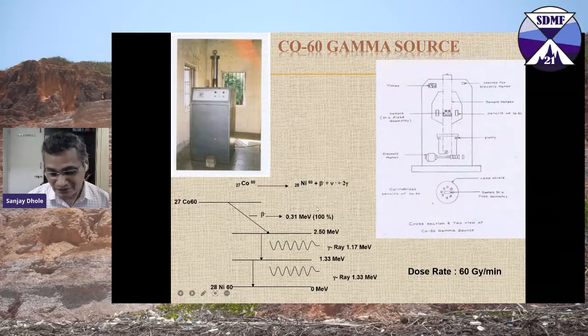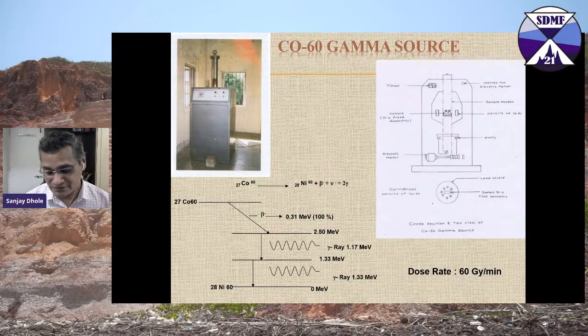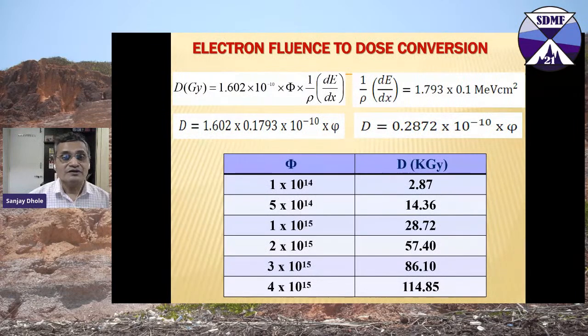So these are all the radiation sources which are available with us, and quite often we use them. There is a conversion factor which is available, because if you go for electron irradiation or ion irradiation, you can always measure the fluence. But if the electron fluence is to be converted into dose, in gray or rad, then definitely this particular formula: dose equals 1.6 into 10 power minus 10, multiplied by phi, where phi is the fluence, times 1 by rho, where rho is the density.